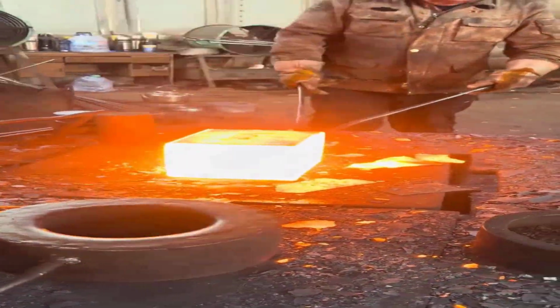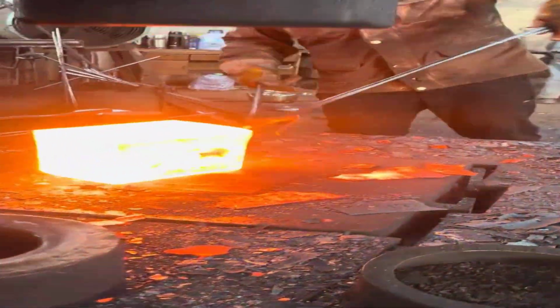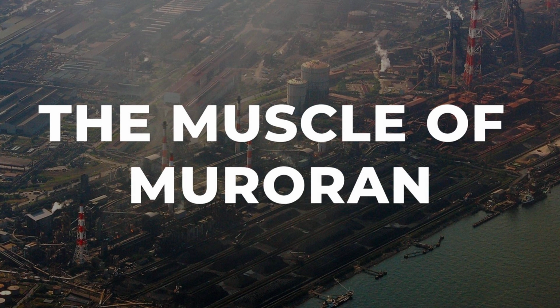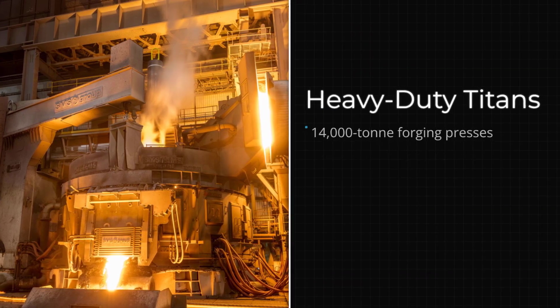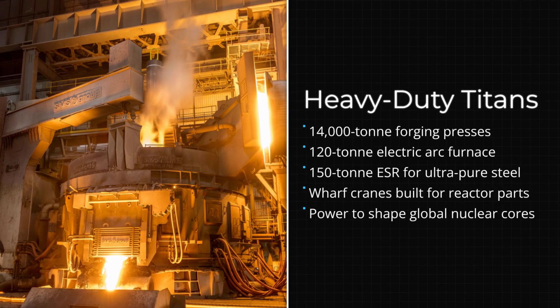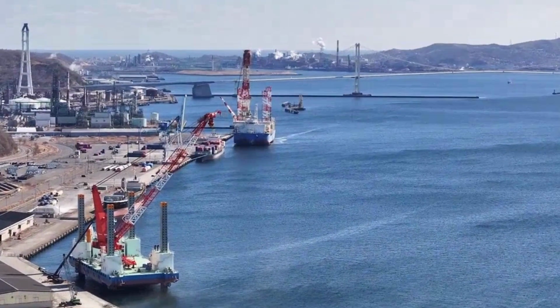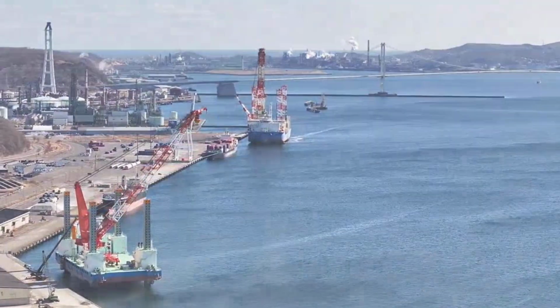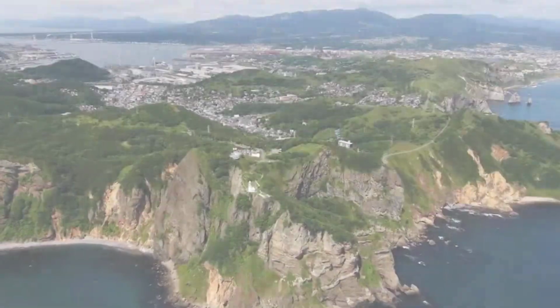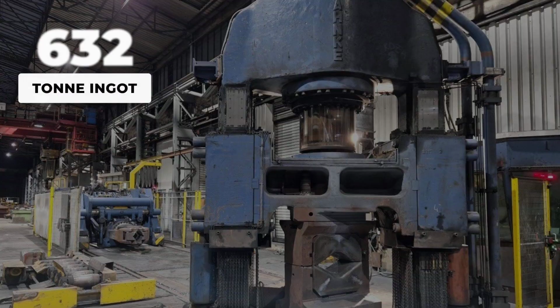Muroran operates two 14,000-ton hydraulic presses, the largest in commercial operation anywhere on Earth. The facility includes a 120-ton electric arc furnace, a 150-ton electro-slag remelting furnace for achieving the highest purity, and wharf cranes ranging from 70 tons to 730 tons of capacity. The plant produced a 632-tonne steel ingot in 2011, the largest commercial steel ingot ever cast.